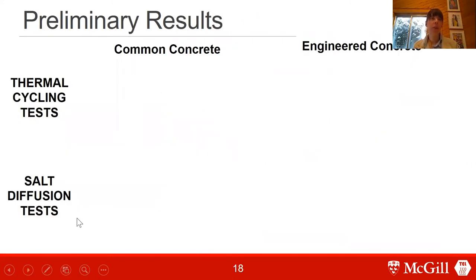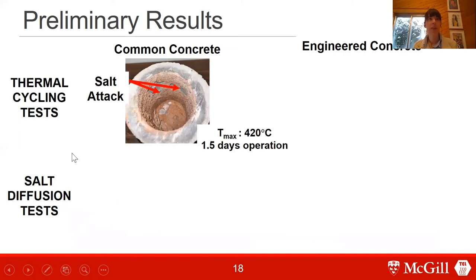And so some preliminary results that we have. So we performed some thermal cycling tests and some salt diffusion tests. If we just consider common concrete, everyday concrete, and look at the thermal cycling, we took our common concrete tanks and cycled over 1.5 days. So we cycled the temperatures and you can actually see that the salt really attacks the common concrete. So the compatibility is not that great. And so we have some issues here in terms of compatibility of the salt with our common concrete.